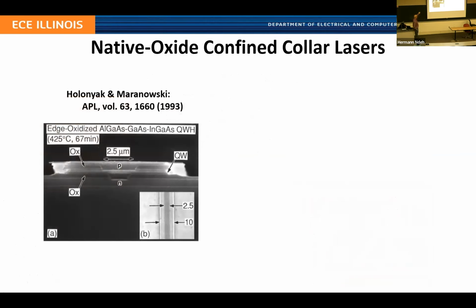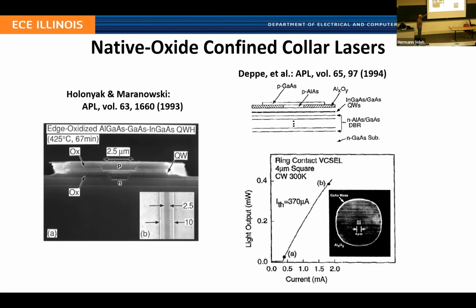Later, it was determined that instead of going from the top oxidizing, you could also go from the edge of the device and oxidize laterally. And this lateral oxidation could similarly be used for index guiding and current confinement to make a high performance index guided laser. And ultimately, Dennis Deppe and his group at UT Austin did this for a vertical cavity surface